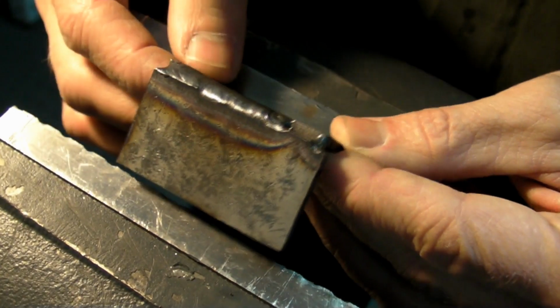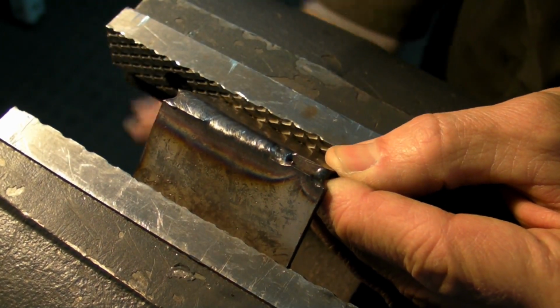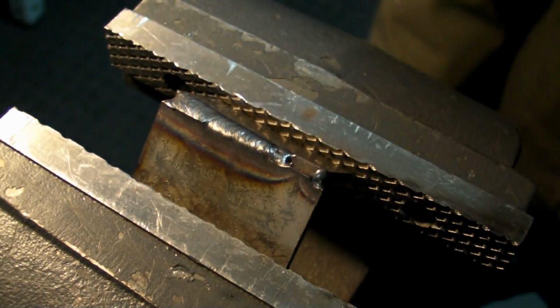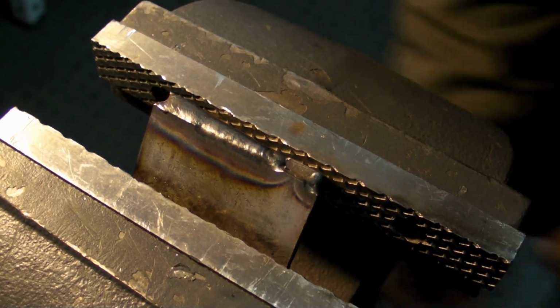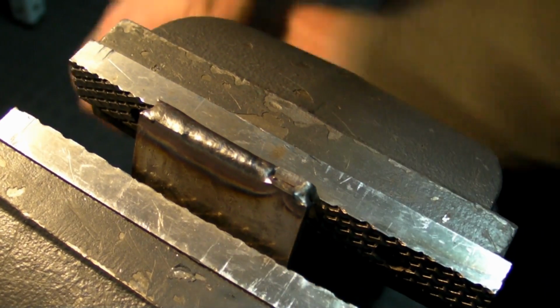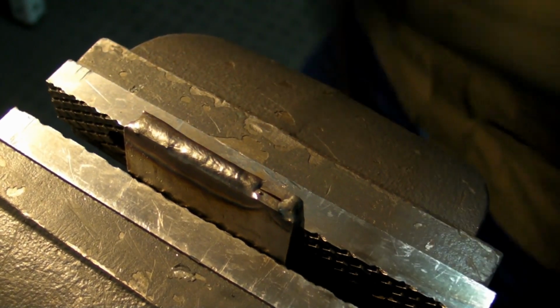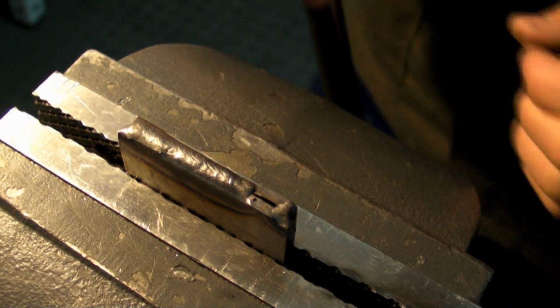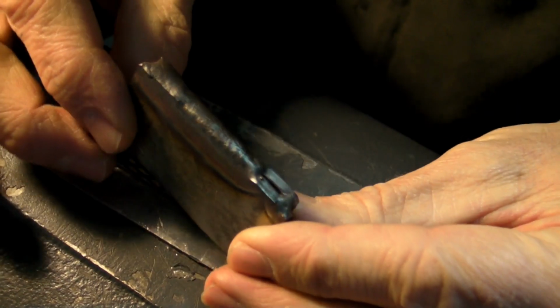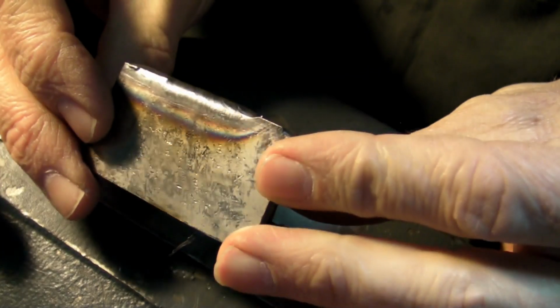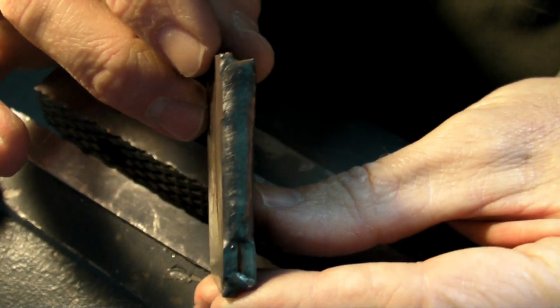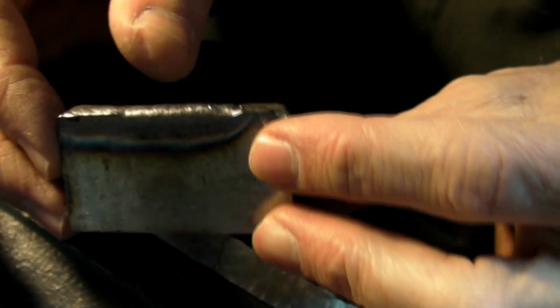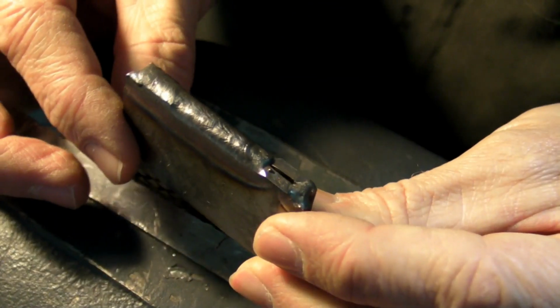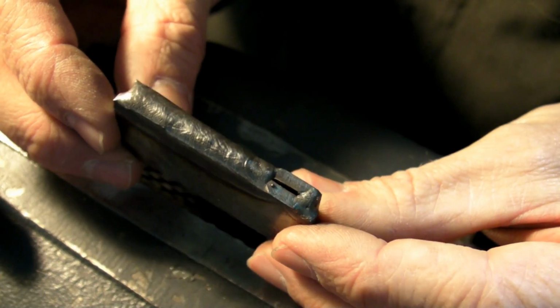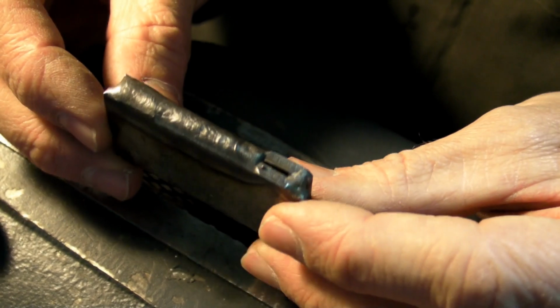Now, this test piece over here will be tested to destruction in the vise, and then this will be given to the boiler inspector. Now you can see this is a stainless steel weld. I'm bending it on itself, and you can see this weld hasn't cracked at all. So that means this weld is ductile, it's good. I'm very happy with this. So this will be marked with the date, and it will become part of the boiler pack. But now I can start welding the boiler, which will be the next part.